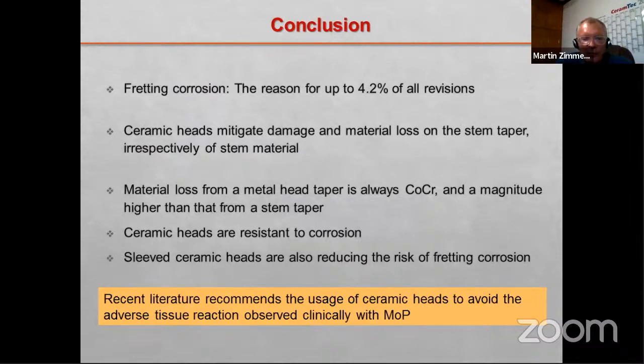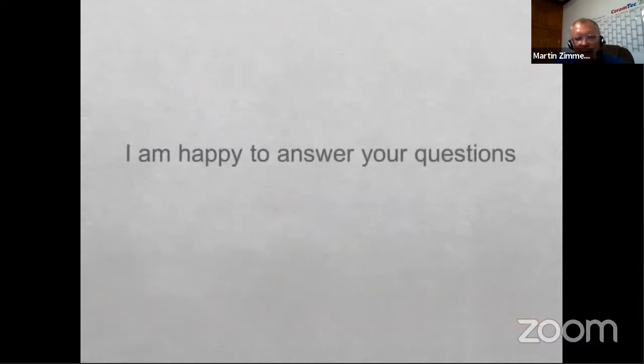The material loss from the metal head comes mainly from the taper of the ball head, and that's always cobalt chrome, and it's a magnitude higher than that from the taper of the stem. So in conclusion, we believe that ceramic heads are resistant to corrosion, and finally, the use of ceramic ball heads reduces the risk of fretting corrosion. This is why, if you look at recent literature on fretting and corrosion, they clearly propose using ceramic instead of metallic heads, even with metal and polyethylene. Now I'm happy to discuss taper in general and tribology and bearing surfaces. Thank you.